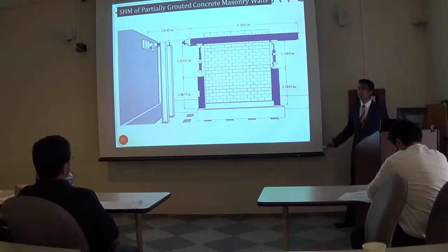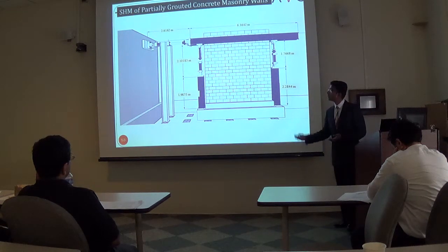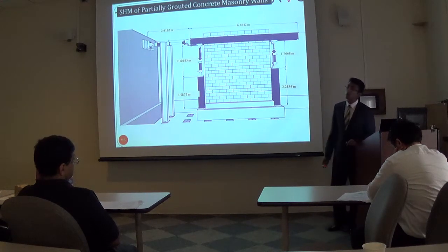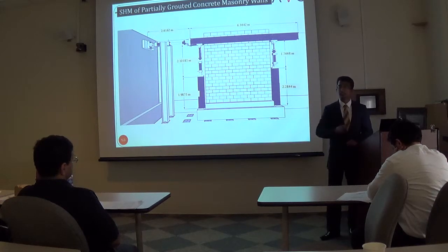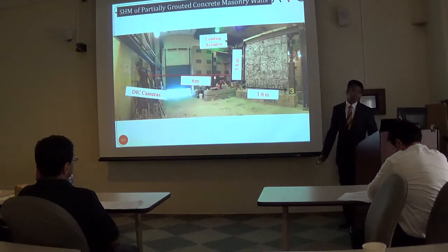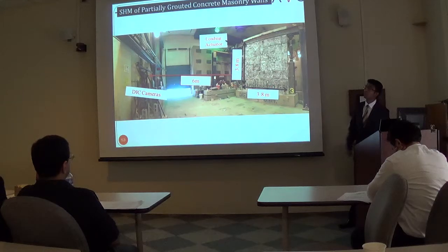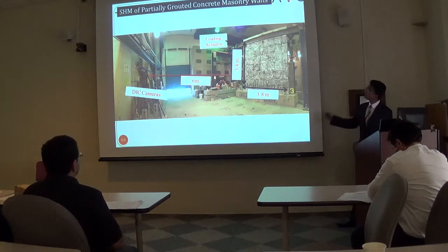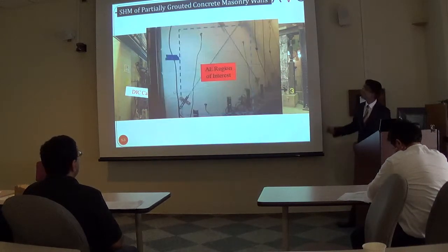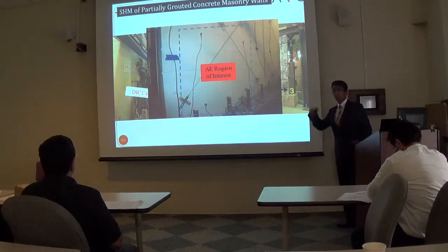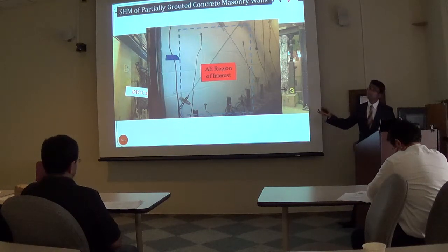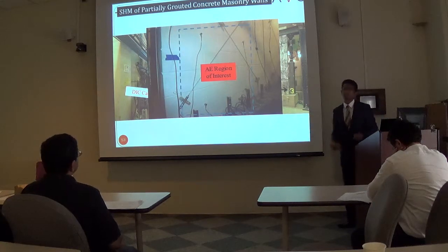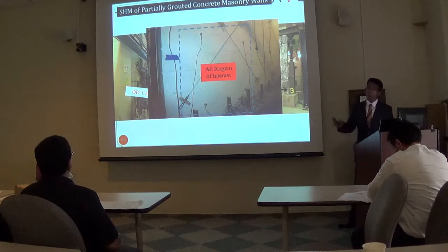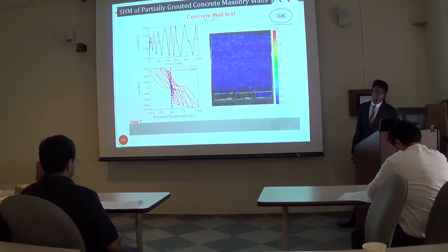The main objective here was to understand the damage development in partially grouted concrete masonry walls under seismic type of loading. For that purpose, DIC cameras were applied and positioned at a certain distance away from the wall, as shown here, and the acoustic emission sensors were also placed at the back of the wall. So the acoustic emission features were then correlated with the DIC features and further correlated to the mechanical parameters to validate the potential of utilizing them for onboard damage detection.